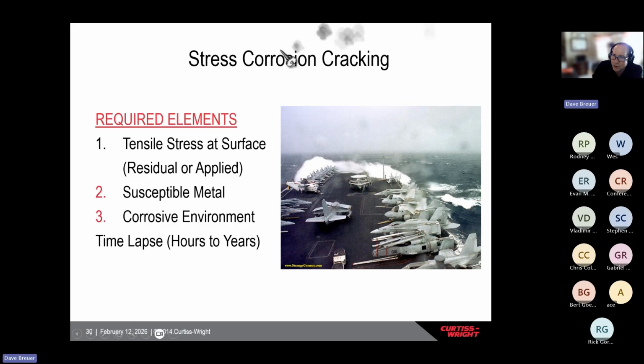To have stress corrosion cracking, you need three or four different things. You have to have a tensile stress, which can come from residual stress like welding, or applied stress like internal pressure in a vessel. You need a susceptible material, which most commonly are 300 series stainless steel and high strength aluminum, and some type of corrosive environment, with the most common being chlorides in solution or salt water. And of course, you need some type of time lapse.